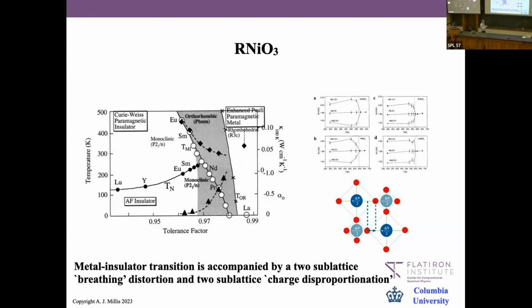These are measurements of just the long and short bonds. And this is associated, in a complicated way I don't want to get into here, with a change in the charge density on the nickel sites. So again, there's an electronic and a structural transition.